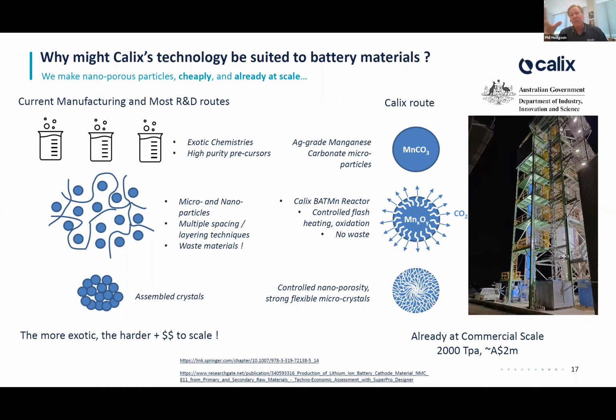So what do we do? If you can remember our toilet roll, what you can see there is a picture of a mini toilet roll, if you like. That's what's called our BATMn reactor, 18 meters high, little 8-inch tube, electrically heated. We just take manganese carbonate, agricultural grade. It doesn't have to be battery grade. I'll talk a little bit about purity in a sec, but we just take agricultural grade manganese carbonate. We grind it to small particles. It gets dropped down that tube. And the manganese carbonate has that trapped CO2 in it, as I described before. That makes its way out, and you then have a very porous material that comes out the bottom. We can control that porosity to give a nano structure, if you like, to these crystals that are microns in size. And so you can see the difference here between an assembled structure and the way we make our structure.